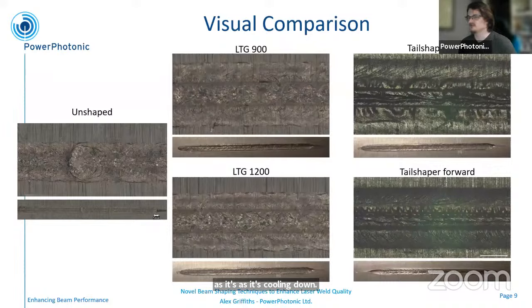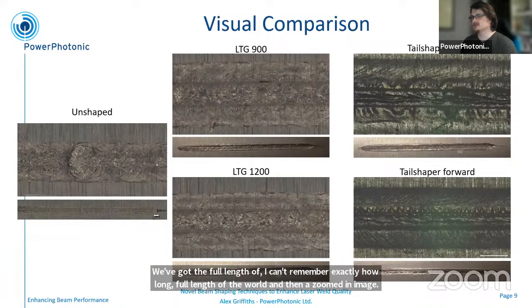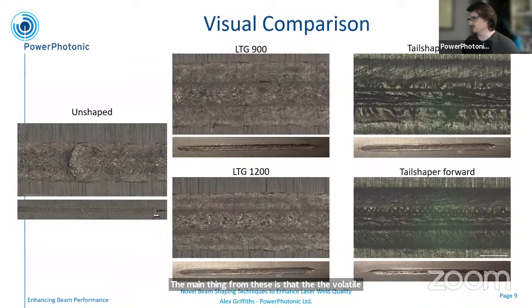So these are just visual images of the resulting welds. We've got the full length of, I can't remember exactly how long, the weld, and then a zoomed in image. The main thing from these is that the volatile nature of the melt pool translates to the visual quality of the weld. The unshaped beam is quite messy, quite unstructured. And then as you go to the LTGs, you've got some improvement. There's some more structure in there, and the tail shapers have a much more defined set of features.